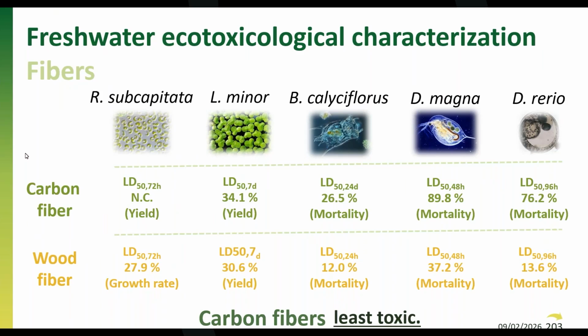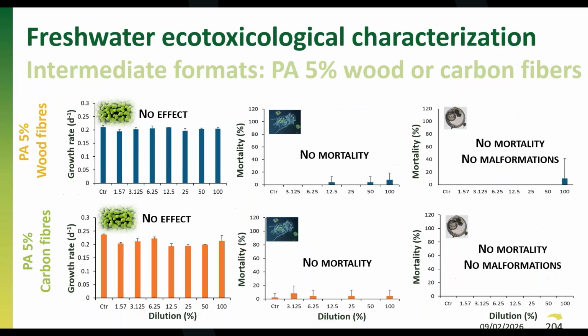But an interesting thing, next slide please, was that with the incorporation of these fibers into intermediate formats, the PAs, that you already also heard about, we did not see any toxicity in these intermediate formats that were composed by the wood fibers and by the carbon fibers. So here in these graphs, what you see in the first ones for the algae is the effects on their growth. So in the x-axis, we have the control and then the different dilutions, and you can see that the growth of the microalgae is equal along all the dilutions, both for the wood fibers and for the carbon fibers,